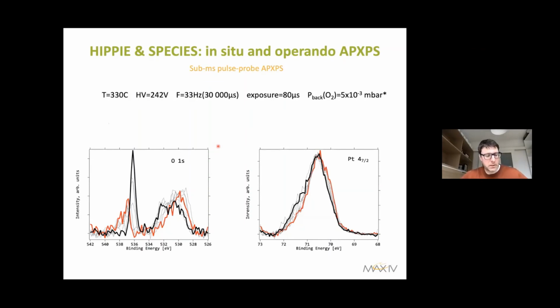Now, the most interesting part: we try to correlate between the surface and the gas composition as this process happens. So we record oxygen 1s and platinum 4f from our sample. You can see in oxygen the gas phase components. Unfortunately, no CO2 production is visible because the noise levels are so high, but we very clearly see a switch between oxygen- and CO-rich phases. For the CO-rich phase, you can definitely see CO on the surface. So these peaks correspond to bridge and top CO, and also you can see platinum CO on top of the platinum peak here.